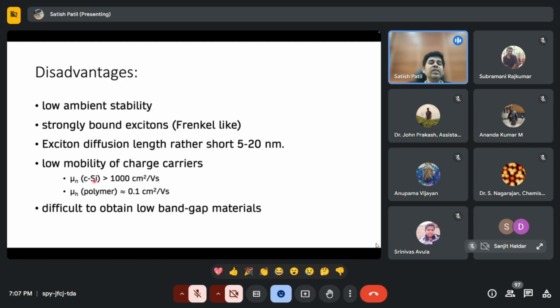For example, crystalline silicon has more than 1,000 centimeter square per volt second mobility, whereas a polymer, even one of the best polymers, is way less than 0.1 centimeter square per volt second. Due to disorder, which I talked about a little bit in my previous slides, where the polymer has a large amount of disorder, the mobilities of these materials are very, very low.